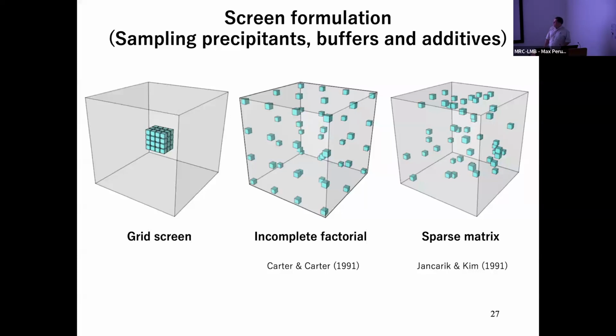Again, that would represent a surrealistic effort, but also, in any case, you have a limited amount of sample in general. So most developments of initial screens are based upon minimizing the number of initial conditions, such as with the incomplete factorial and the sparse matrix formulation. An incomplete factorial, the one represented in the middle, could be defined to some extent as an extended grid screen with combinations omitted randomly. So there are different ways to do this, but basically, you want to expand the grid screen somehow. For that, you either miss some components or you miss some concentrations, but you just find a way to do that.